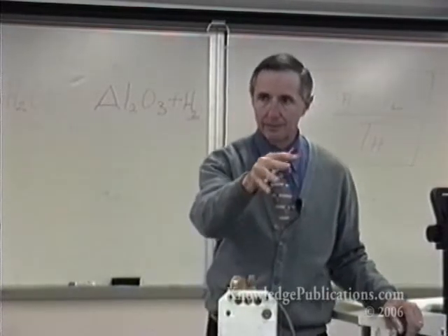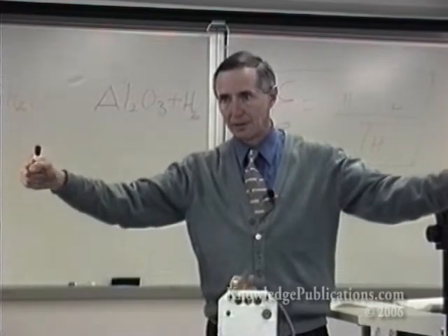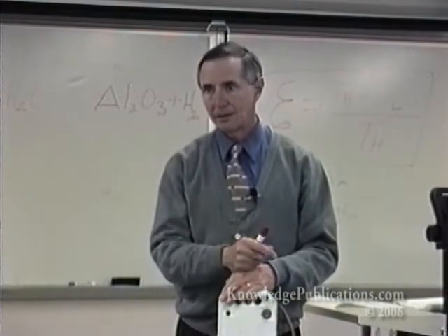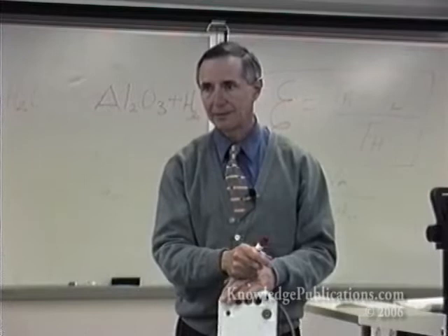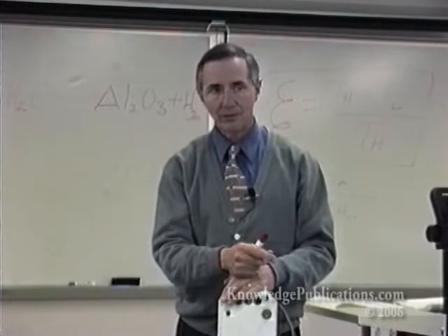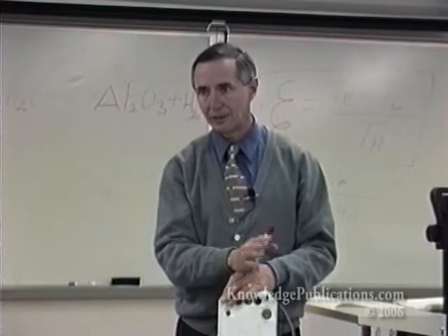The hydrogen will enter the lattice, it'll stay parked there for a while, start making atomic out of ionic and diatomic out of atomic until it grows and produces internal pressure and makes the metal behave in a brittle fashion. But if you also do what the plating house does, and that is to bake the hydrogen out, then you're safe. Right after plating, a good plating house will immediately bake out as a procedure. They'll put it in an oven and hold it for a while, bake out any hydrogen, after which they have great success with the ductility of the metal and the adherence of the plating.